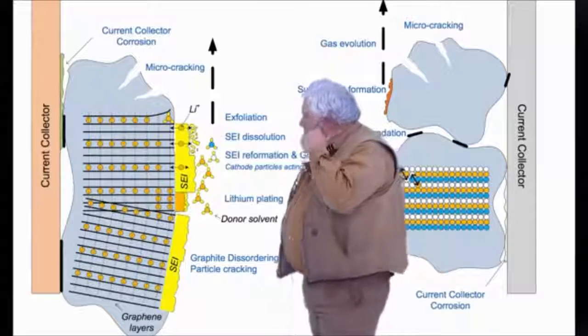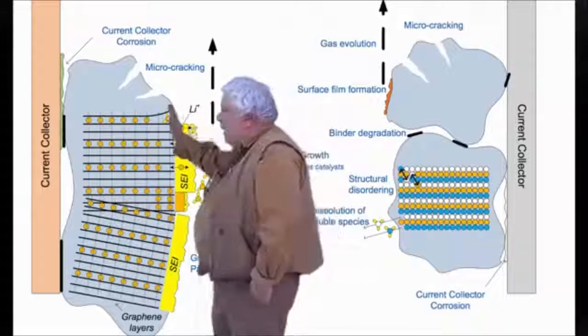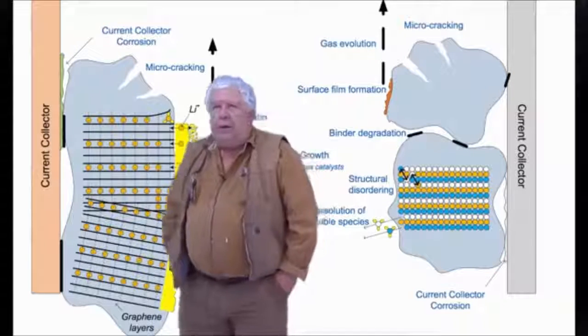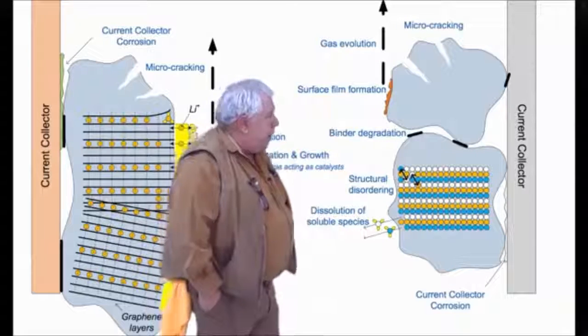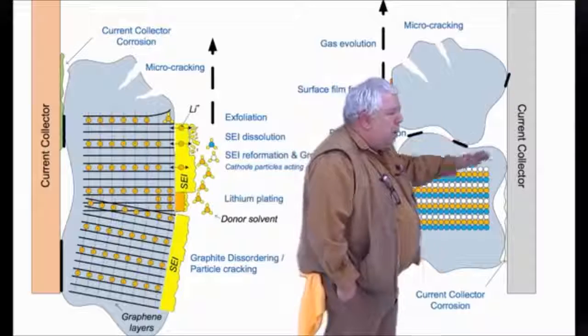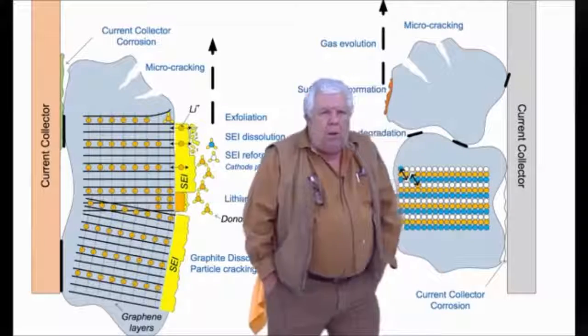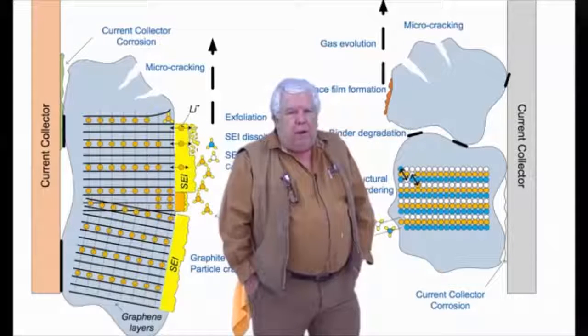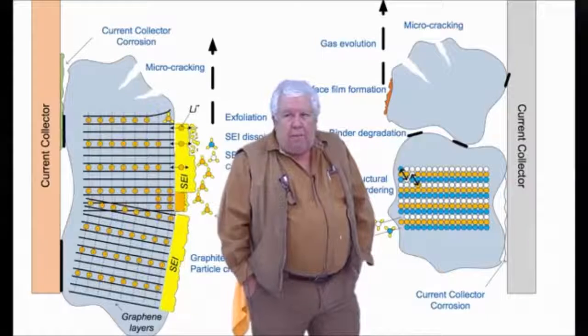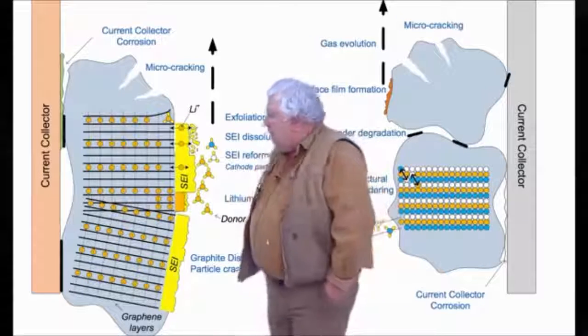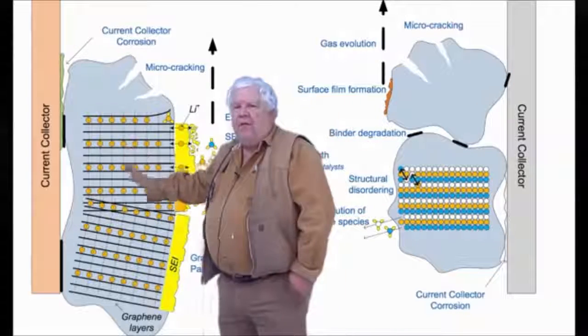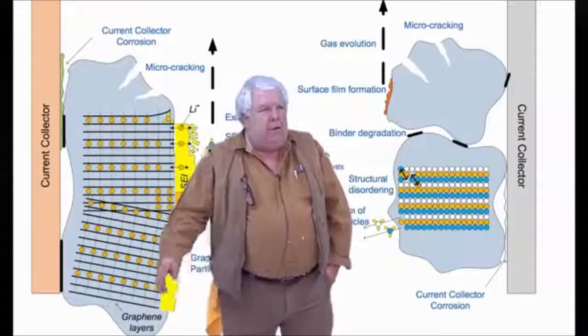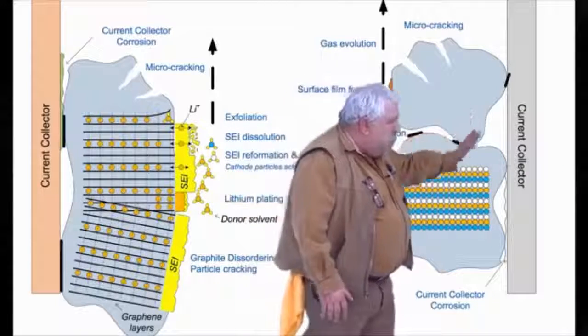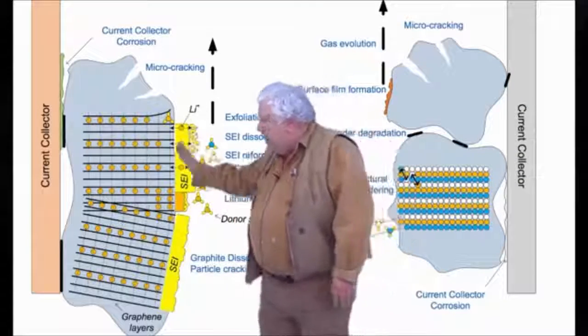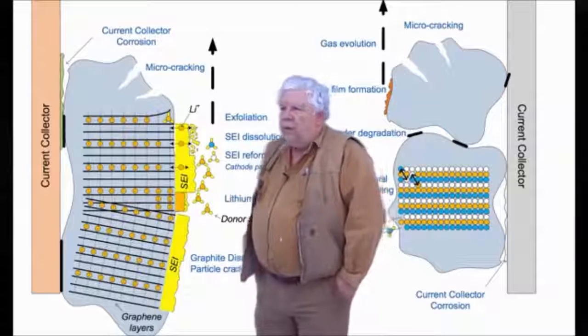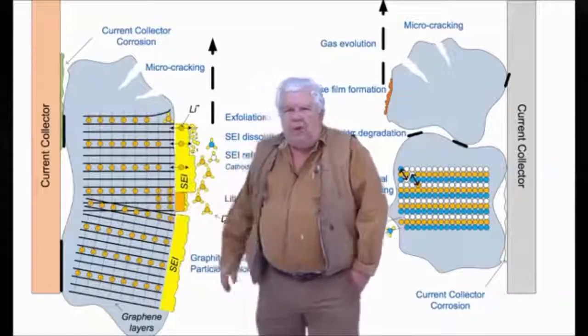We can store a lot of lithium ions in this carbon. And to give you an order of magnitude there, the iron phosphate can typically store about 170 milliamp hours of cations per gram. The carbon is actually much more capable at about 372 milliamp hours per gram. So it's over twice the thing. Now, they'll adjust that by having more of the lithium iron phosphate and a thinner layer of the carbon. But normally, you'll have more storage here than you have over here.